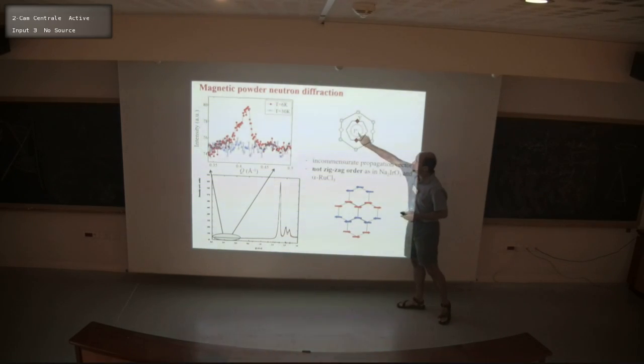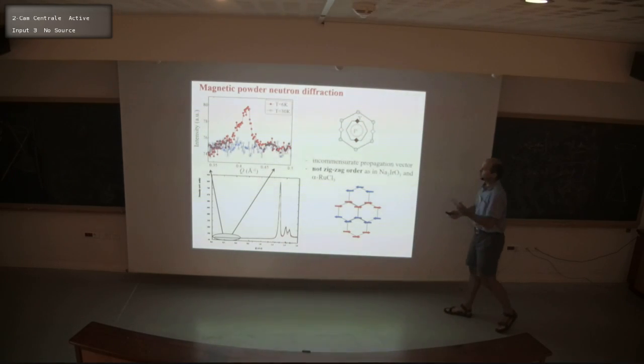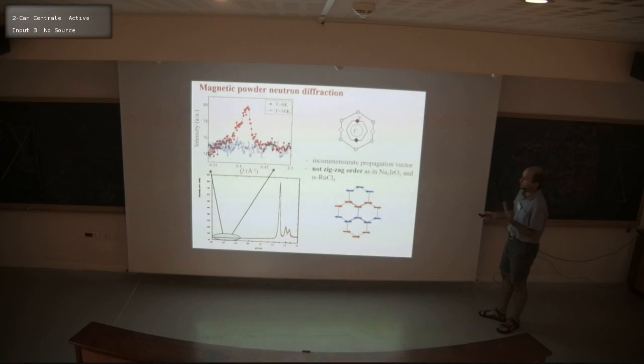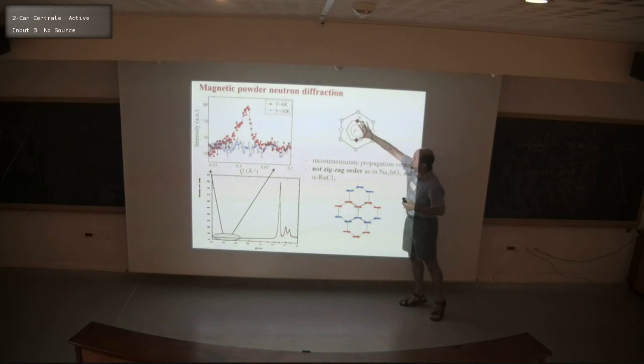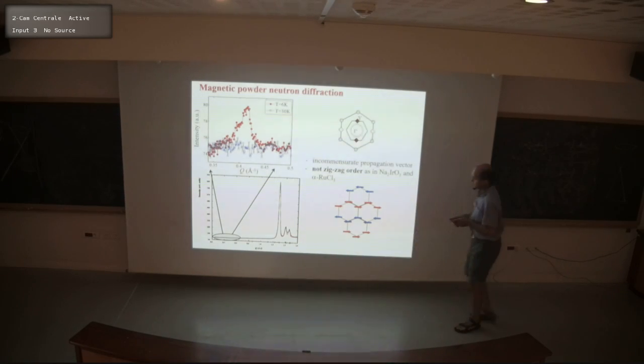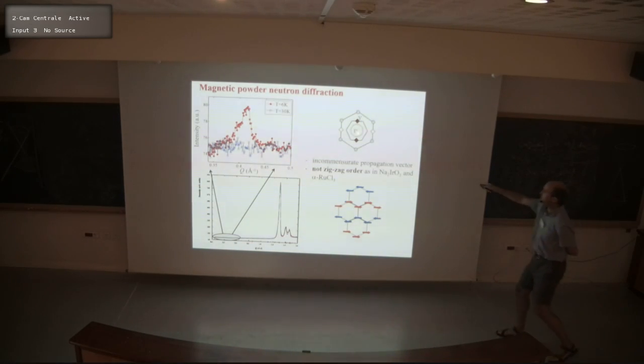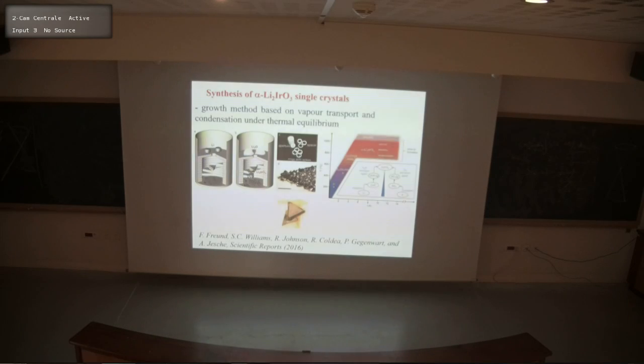So we know the wave vector is located somewhere inside the Brillouin zone, but it's very different to the wave vector for commensurate ordering, as I will show later, for sodium iridate and also ruthenium chloride, where the ordering wave vector is at the midpoint of the zone boundary. So in order to make progress and really find out what the magnetic ground state is, there's many possibilities. The Q vector could be anywhere on a sphere, in principle, in three-dimensional space.